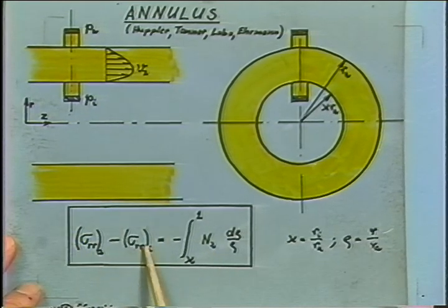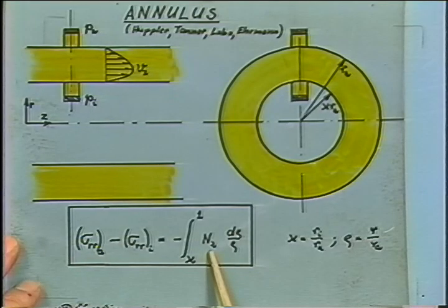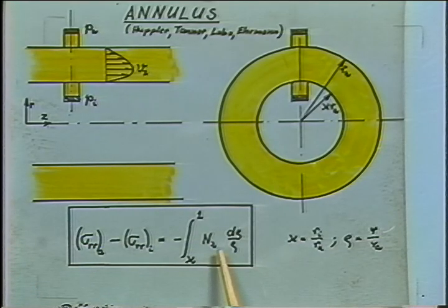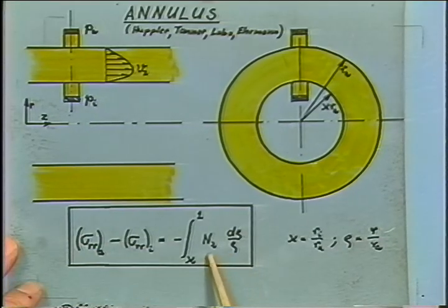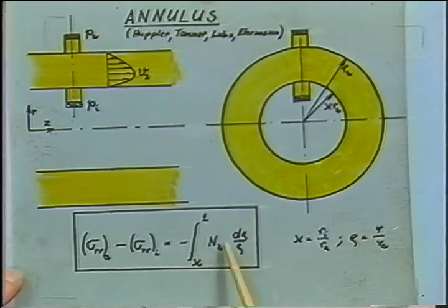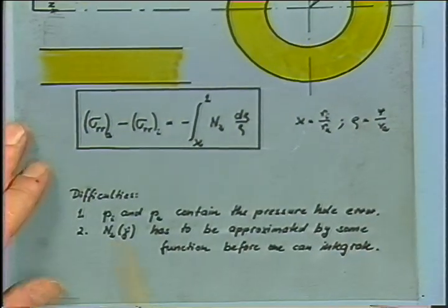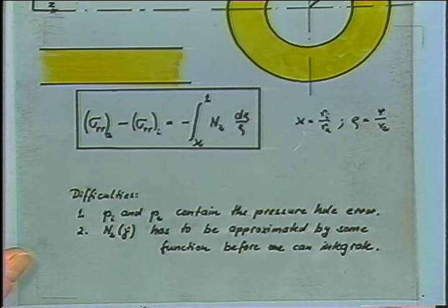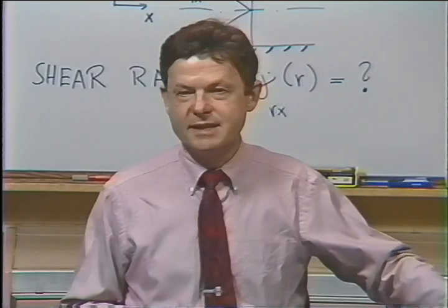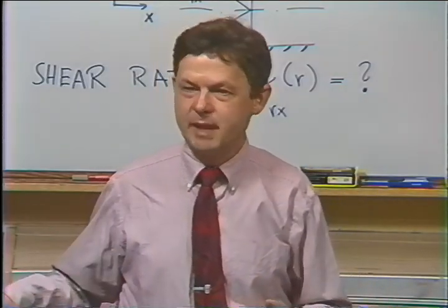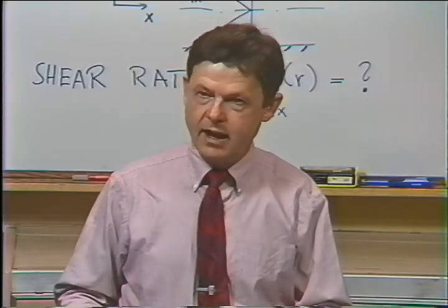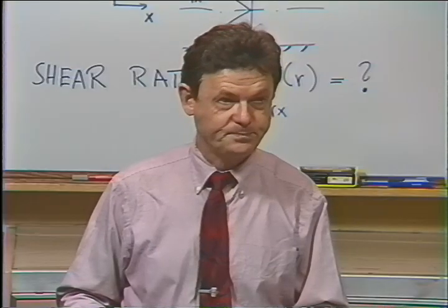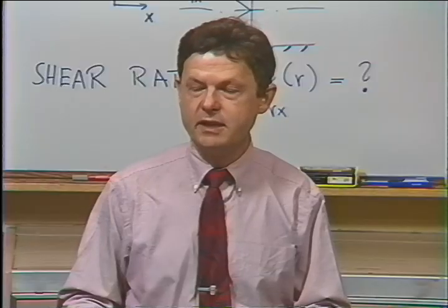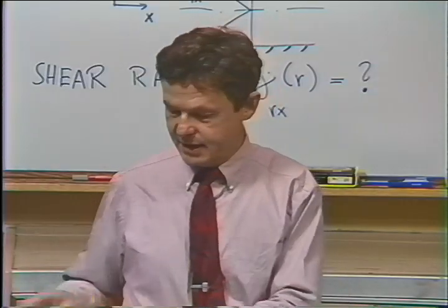This could be measured in an experiment, and it has been measured, but for the analysis of this integral, you would need an estimate of the function. You would take a guess of the function for N2 as a function of shear rate. And then you would put your power law solution in for obtaining the shear rate, and then you would calculate this and obtain, as a result, N2 as a function of the shear rate. So it's not a pure experiment in the sense that you have to enter a model for the kinematics which will bias your result. Also, the normal stress differences are fairly low, and the pressures in the capillary are fairly high. So the experimental error will be significant in that experiment. It's very hard to get data from this.